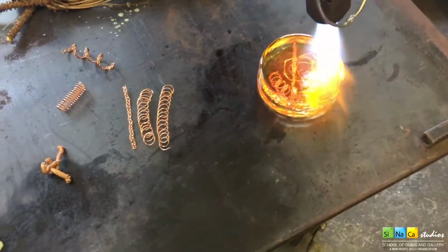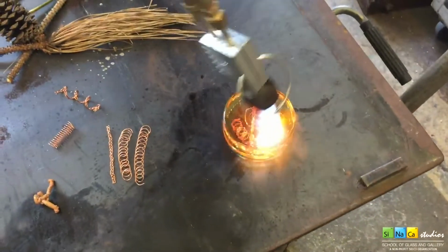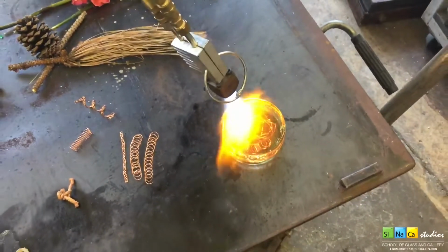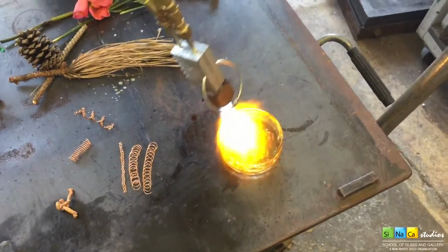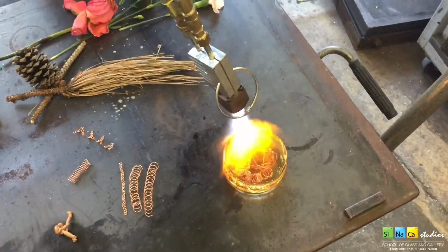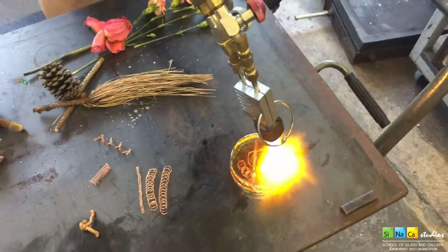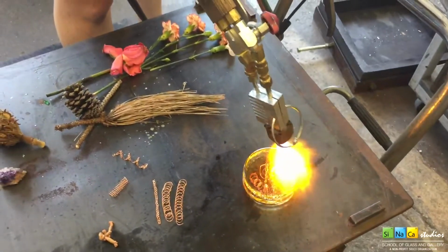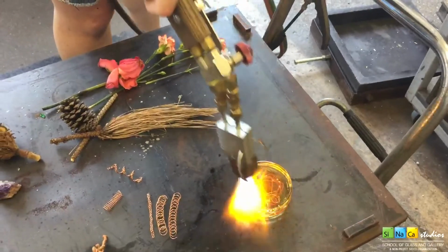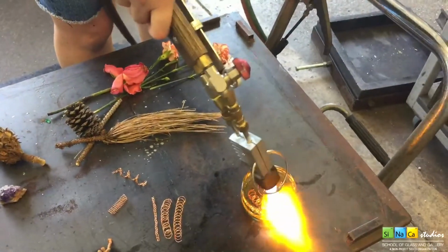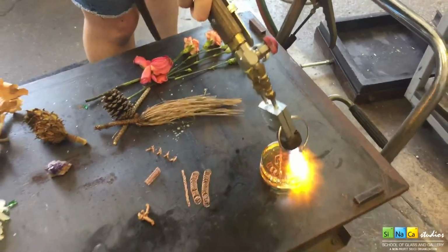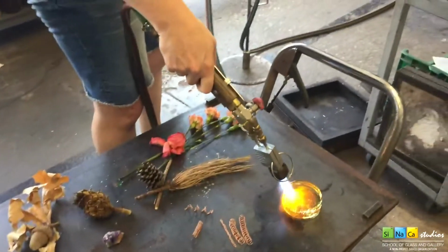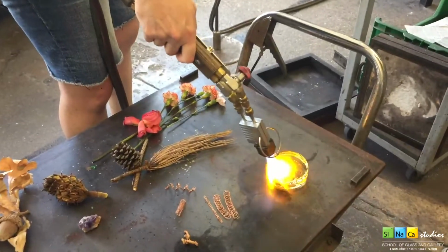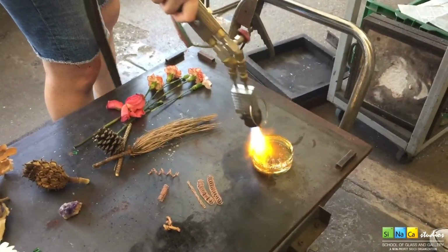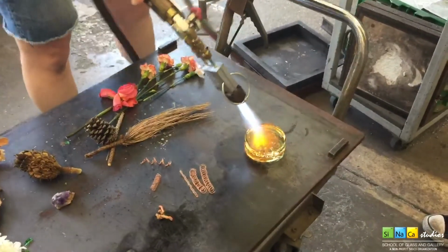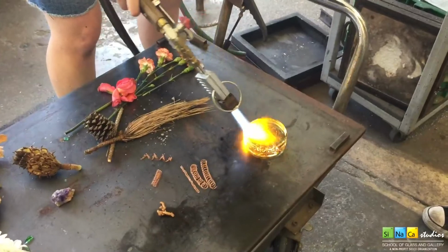So a lot of metals don't work very well with glass, but generally if you keep your metal wire very thin and you're not using very, very big chunks, the glass will kind of tolerate it. Copper wire is the best, and copper sheet is the best for this though, because they cool very, very similarly to the glass. So they're not going to shrink too much more than the glass does as it's cooling down, which is really what ends up causing problems for most metals: the metal tends to shrink way more than glass does, and it tends to pull away and crack the glass as it's trying to shrink.